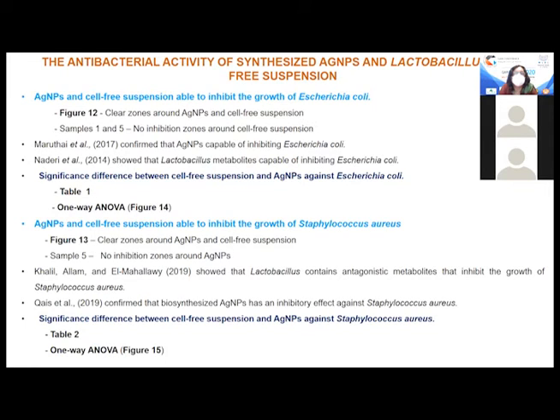Also, clear zones around silver nanoparticles and cell-free suspension show that the silver nanoparticles and cell-free suspension were able to inhibit the growth of E. coli. But for samples 1 and 5, there were no inhibition zones. According to Table 1, AgNPs, the silver nanoparticles, showed higher inhibition zones against E. coli than cell-free suspension. And one-way ANOVA further confirmed a significant difference.